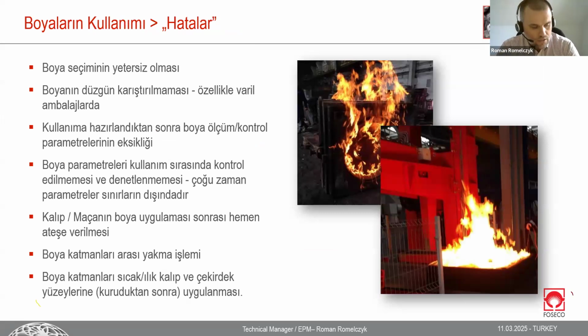Of course, what I already explained, if the coating is not properly selected. Very important is that you have a chance to see the recipe itself, with 10, 11, 12 different materials mixed together with different weight and different density. So it's obvious that this coating always needs to be super precisely mixed before use, to be sure that all materials are mixed together and have a chance to work together. So this is an observed mistake, that it's not properly mixed.